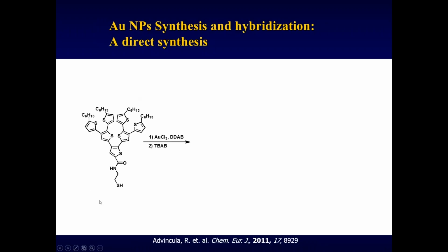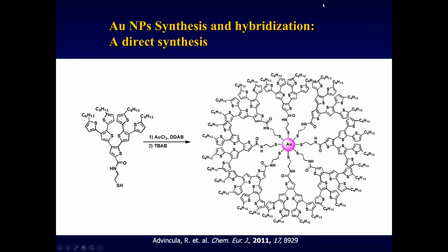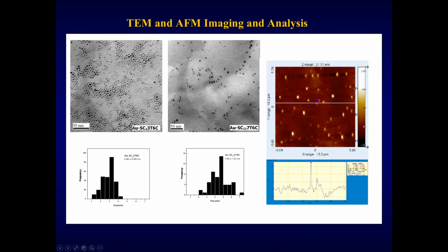In this case, we were interested in the quenching mechanism of the plasmon absorbance with the dendron. And here, for example, we synthesized dendrons of different chain lengths of alkyl-thiophene spacers. So we have 2 carbons versus 11, for the 7T and 3T. And the synthesis is basically a direct ligand functionalization of the gold chlorides versus exchange that was done in the previous example. So we use this basically as dendron ligands.